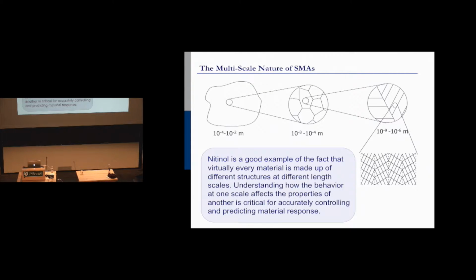So you can imagine at the very small length scale, remember I talked about those variants? You could either have a tetragon like this or like this. So here's one variant, it's a tetragon like that. Here's another, here's another, here's another, right? So you've got two variants that are matching. Okay? So you can have variants that are twinning. And those variants can exist in a little tiny band of martensite that can form what's called a habit plane with the austenite. So this is the monoclinic, this is the cubic, another martensite. Those are going to form another habit plane with more austenite and martensite.